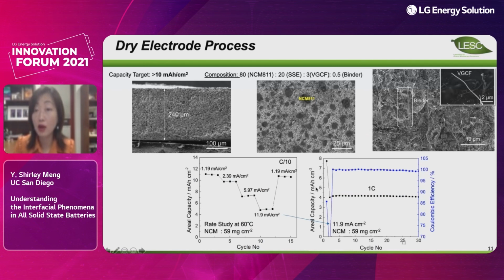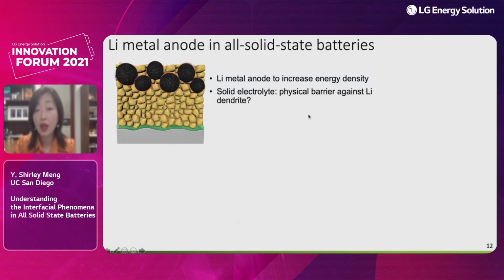So this is recent data in one of our archived papers to showcase that high loadings are possible in the NMC cathode. Yes, the temperature here is 60 degrees Celsius, but please be reminded that we have more than 10 milliamp hour per centimeter square loading for the cathode.